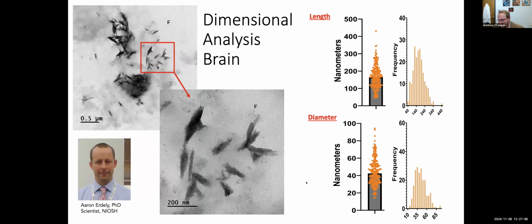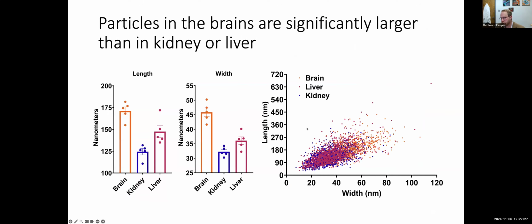Aaron Erdely at NIOSH and a team at R.J. Lee in Pittsburgh have been doing the manual measurements of the length and width of these. And you can see that here in the brain, you've got a median of about 170 nanometers by about 45 nanometers in diameter. When we look at this head-to-head, now we're comparing brain, liver, and kidney from 5 different subjects where everything's been manually measured, 200 particles or more per subject per organ.